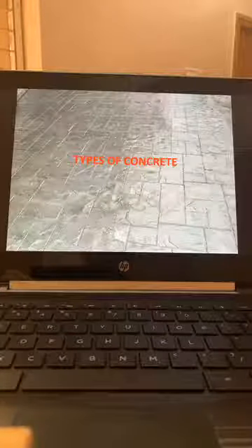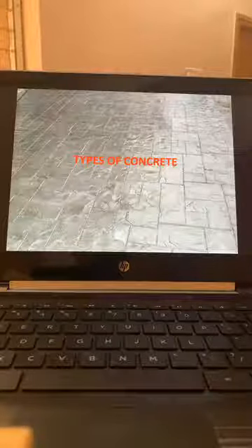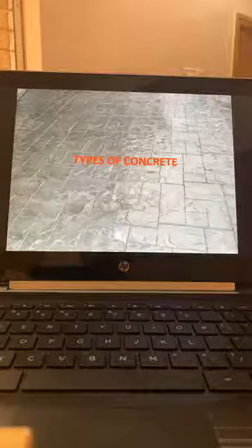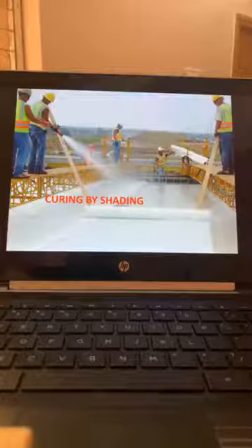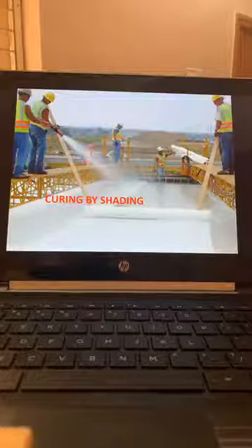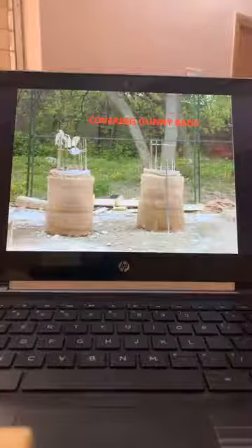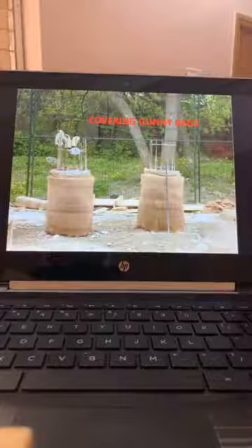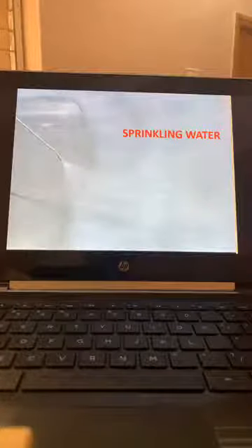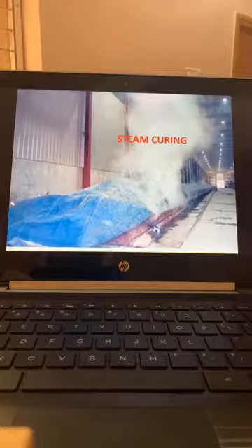Now we will go to types of concrete. Some cement companies are offering sheets for curing — these are basically membranes. You apply moisture and spread the membrane to keep the moisture, but it has to be breathable. Steam curing is used in most precast plants because the element needs to be stripped and shifted. In the evening we cast the concrete; next day morning we shift it. I have been using steam curing for the last 30 years in precast spun concrete poles — electric poles — and they all use steam curing.